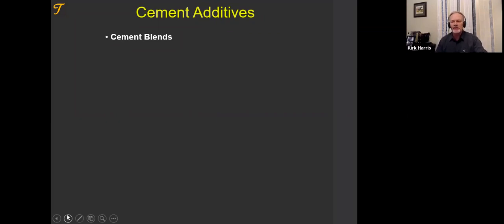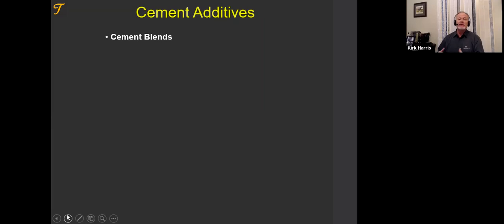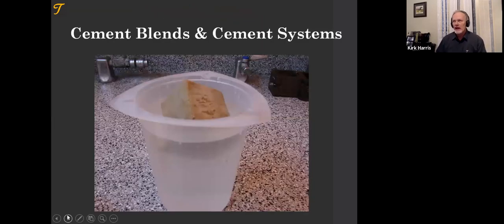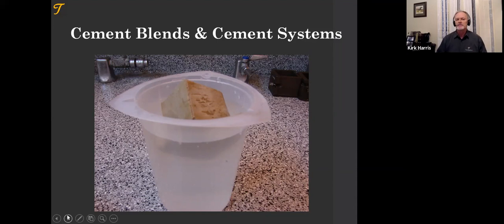A word about cement blends: the pozzolan with the cement and bentonite — probably a 50/50 pozzolan blend, half-and-half cement with a couple percent gel. The 50/50 pozzolan is a great tail slurry. We usually use 65% cement, 35% pozzolan with 6% gel for a lead. Cement blends can be leads, but they can also be silica flour for HPHT wells and general type blends. This is a cement system that floats — it contains hollow spheres. Just because a system has a name doesn't mean it's good.